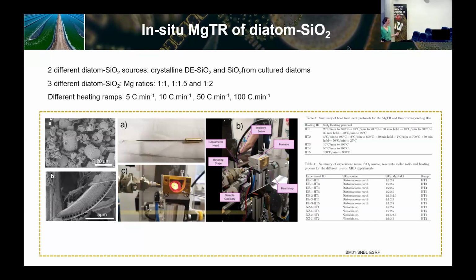They have a very nice setup for this kind of experiment. You can do fast heating, you can heat up very fast actually. We put the material inside a sapphire capillary and did a lot of tests to see what happened. This has to be, of course, loaded inside a glove box because the magnesiothermic reduction happens in an argon atmosphere. So I will go very quickly through this.